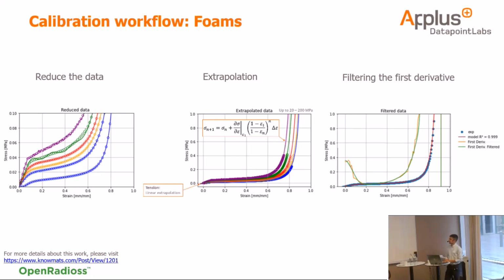For the foam, the process is more straightforward. You have a bunch of data directly from the experimental side. In this case, it's strain rate dependent, so we have a bunch of curves. Then what we do is reduce the noise and the number of points. We extrapolate the data up to usually between 20 and 200 megapascals, depending on the contact surface and so on. And at the beginning, we extrapolate the tensile. For this particular model, I think we can also introduce a tensile curve, but we usually go this way because the application is more for impact.